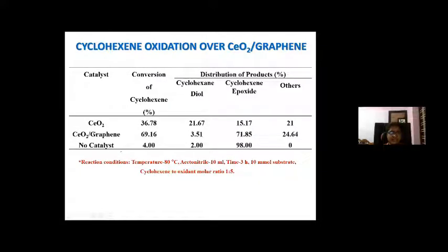Next, we go to the cyclohexene oxidation reaction. We tried the reaction with pure ceria as well as ceria incorporated graphene. We cannot use graphene alone for the reaction because the graphene dispersion remains a homogeneous mixture even after hydrothermal treatment, so we cannot recover it. We cannot use it as a heterogeneous catalyst. So we tried the reaction using ceria as well as ceria graphene. The incorporation of graphene into ceria enhanced the catalytic activity and also the selectivity towards cyclohexene epoxide. The non-catalyzed reaction is not much active.